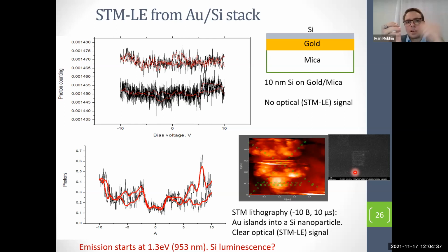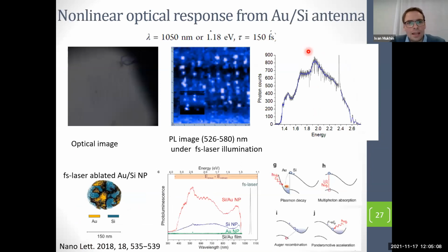We excite a nicely localized gap plasmon on the same tip, the energy of which converts to photoluminescence from silicon. So these experimental results show that the most compatible material can be applied for fabrication and development of an electrically driven nanoscale optical source. And the last part, just a few slides: this hybrid gold-silicon nanoantenna can also emit light, demonstrating a very broad photoluminescence spectrum under femtosecond laser irradiation.